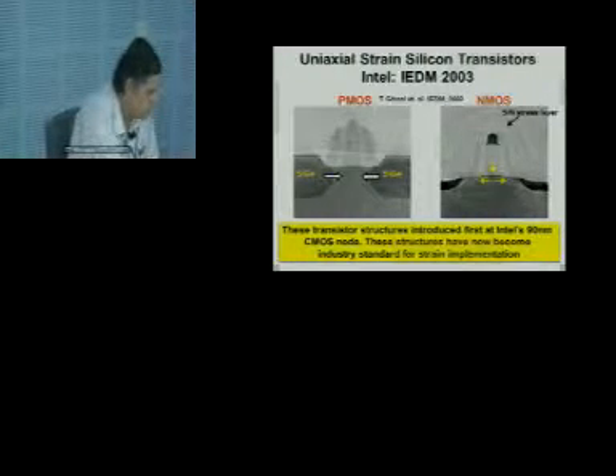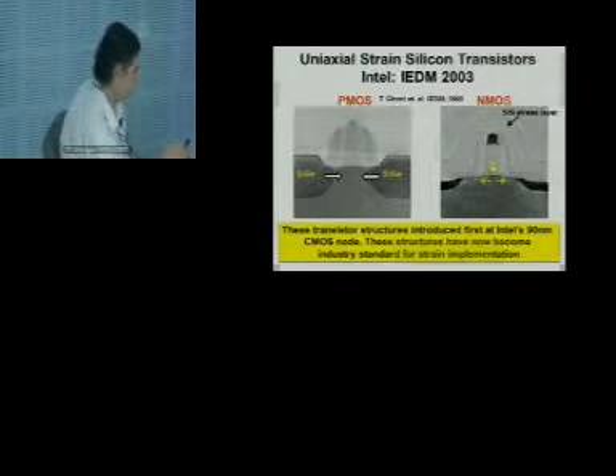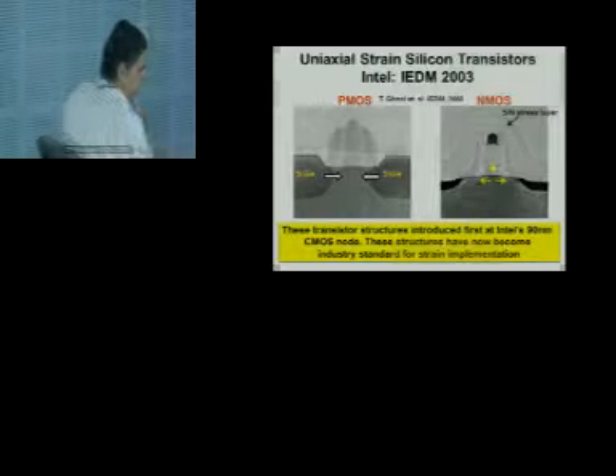This is important: the channel region of silicon in the PMOS has a compressive uniaxial strain. It is done by silicon germanium epitaxial deposition on the source drain side, and because of the bulk expansion of silicon germanium, the region in between the channel gets compressed, and it is a uniaxial strain. As a result, the hole mobility in this region is improved, and such a PMOS works better than ordinary PMOS.